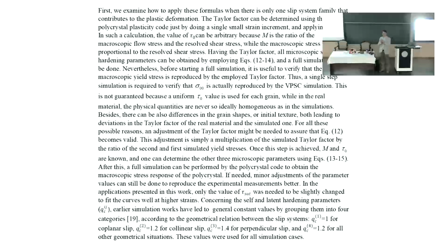So we only reduce to 4 parameters, and they are increasing—the easiest one, coplanar, we give a parameter value equal to 1. For collinear, 1.2. For perpendicular, 1.4. And then a kind of average value for all the other classes. So it's a huge simplification, but efficient and reasonable. Testing shows that it actually leads to extremely good results, so that can be used in the simulation.